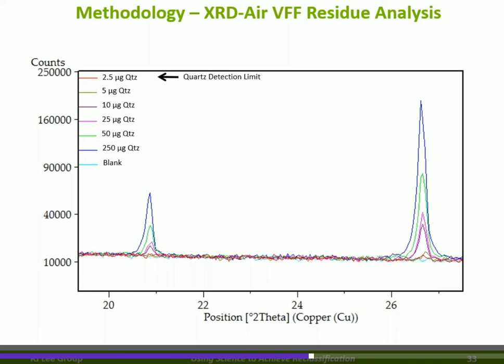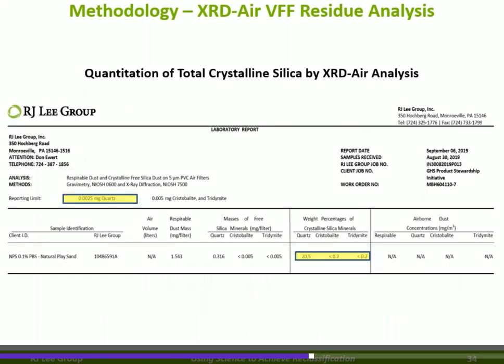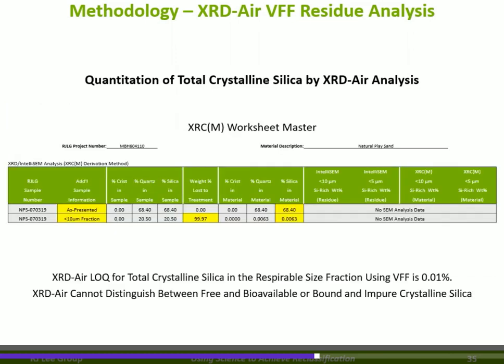If you look at the very bottom right, at the bottom of the peaks, that red line just above the blue one, which is the blank, is the 2.5 micrograms. Extreme sensitivity. We've split the 3 milligrams in half because we're going to run it on 2 different methods, and I'll show you the second method in a minute. So we gave XRD air 1.5 milligrams on a filter. We run it to the 2.5 micrograms per filter detection limit, and we get a weight percentage in the end. We find that that 1.5 milligram fraction contains 20% crystalline silica.